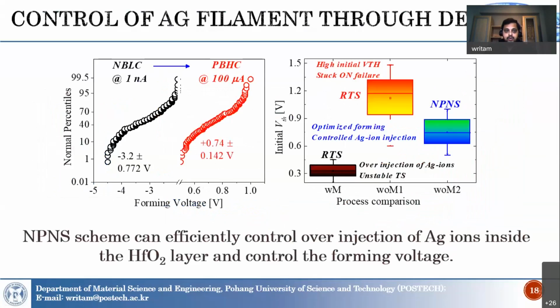So what is this scheme actually? Before applying the positive voltage on the silver electrode side, if you apply the negative voltage, what happens? The soft filament, or rather you can say oxygen vacancy filament, forms inside the structure. Then you apply the positive voltage, and it becomes a silver filament. So it starts as a vacancy filament, and then switches to a silver filament.